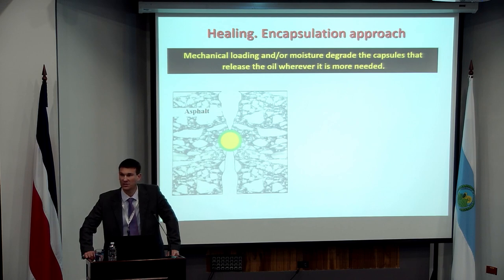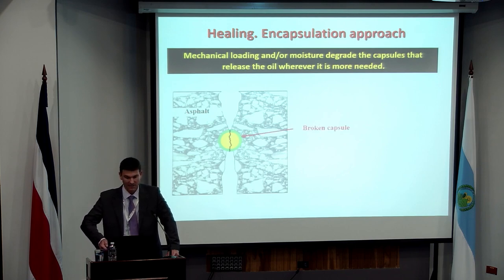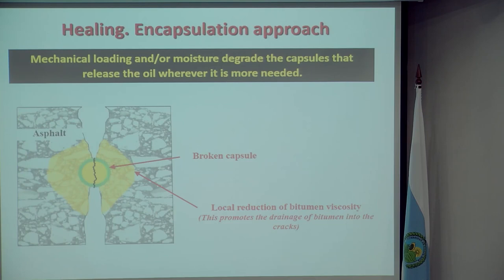In other words, the philosophy there is once the road starts to fail, water will get into that road in some particular form. Once it actually hits the capsule, it will reactivate the capsule in terms of releasing its fluid. When that happens, the capsule will break. It will then locally reduce viscosity by releasing its healing agent. That healing agent is probably going to be a low viscosity oil type product. And we're playing around with lots of different materials. We're playing around at the moment with sunflower oil, so something that's relatively cheap to acquire, and seeing what that has in terms of its effect on healing. And obviously, once that material is soft enough to flow, because of the nature of an asphalt material as a self-healing material, it will flow and it will heal.